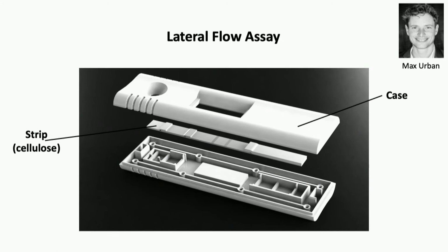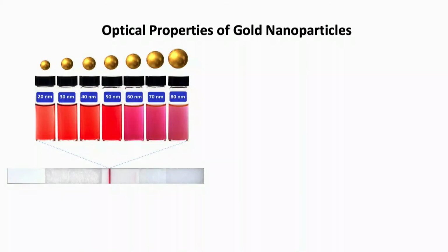What Lynn and Max then came up with is to use them in lateral flow assays because of the strong color response that we get. Lateral flow assays you've already seen in Lynn's pitch, as a cellulose strip and sometimes a casing, and the most prominent example are pregnancy tests. However, for viral tests or any other diseases, these don't really exist because generally the concentrations of these in the bloodstream are too low. Most often gold nanoparticles are used in these strips, as you can see here with the red color, and they're gold nanospheres.